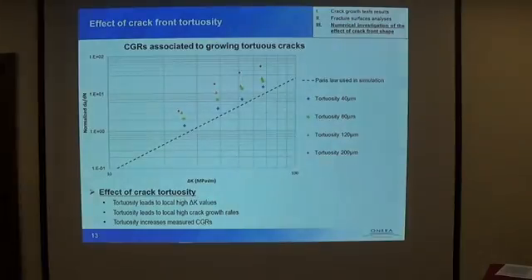Now we apply the DCPD method during the crack growth algorithm. With the dashed line, you have the Paris law, which was used to locally drive the crack growth rate. And the different points you see correspond to the crack growth rates that were measured using the DCPD technique during the numerical crack propagation. And you can see that the tortuosity tends to increase the measured crack growth rates.